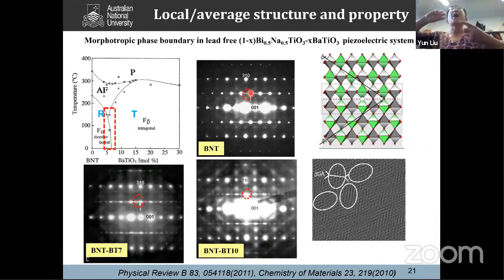That tells you the octahedral rotated around 111, around 111 actually has this kind of ordering. If we're using the green to indicate the octahedral rotation this way, and then green is rotated the opposite way. So if we have a green, this kind of octahedral tilting ordering.